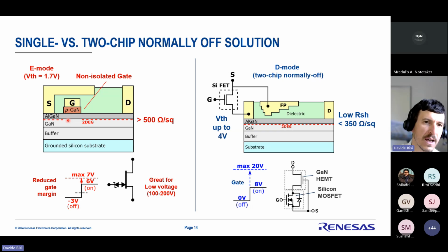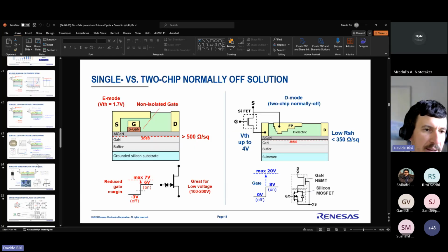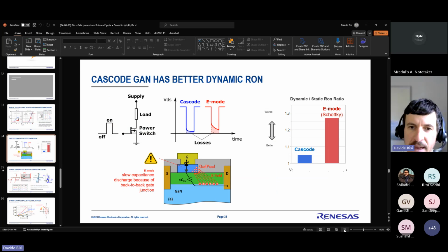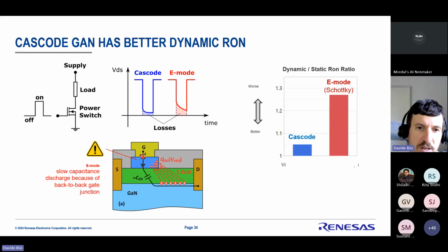The next generation of E-mode devices put a Schottky contact between the gate and the p-GaN to minimize the gate leakage. But now, with a Schottky contact between the gate and the p-GaN, you start having a back-to-back junction. You have a junction between the p-GaN and the 2DEG, and a junction between the p-GaN and the gate. Now, if I go back to this slide here, with a back-to-back junction on the gate, when it's time to charge and discharge the CGD, current now has to flow through a back-to-back junction. And that's not easy. Current here is blocked in both ways.